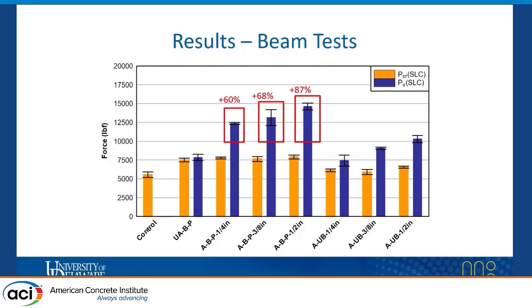The purple bars demonstrate the ultimate capacity of the SLC group. When quarter-inch anchors were used, there's an increase in ultimate capacity relative to the unanchored strengthened beam of 60%, whereas there is an increase in ultimate capacity of 68% and 87% for the 3/8 inch and half-inch anchors, respectively, compared to the unanchored strengthened beam.